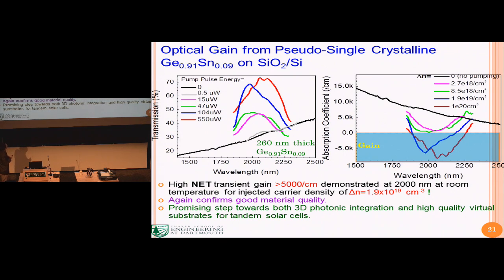You can convert this kind of curve into the gain estimate. You can find that basically this negative absorption over this region is optical gain. The material can actually get a pretty high optical gain, on the order of 5,000 inverse centimeter. So this again proves the high quality and the potential for using this material as a light emitter for photonic integration. And also, if you can make a laser with the semiconductor material, you can also make a good solar cell. So basically, this is proving the concept that this idea works.